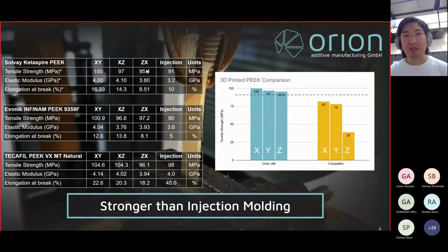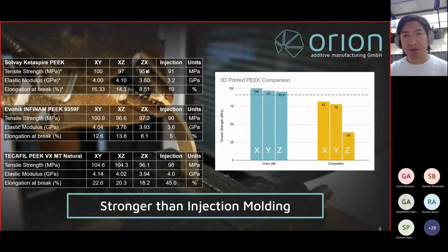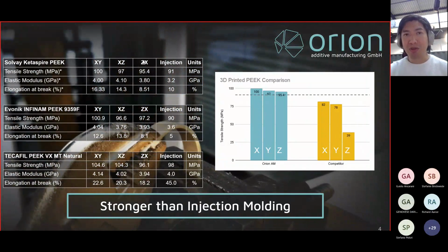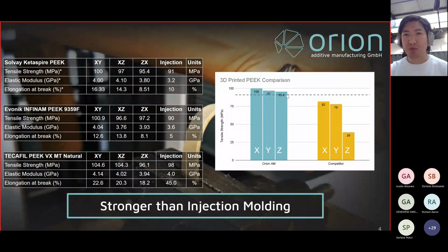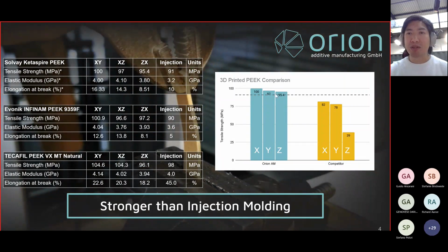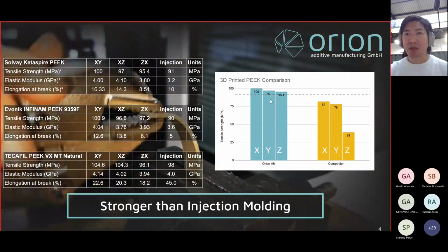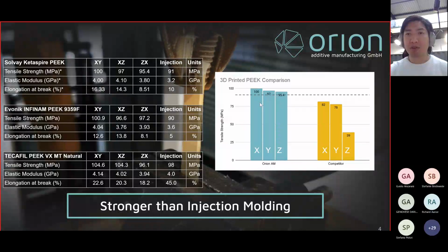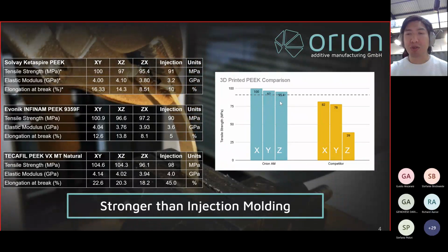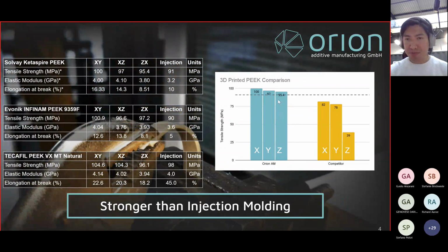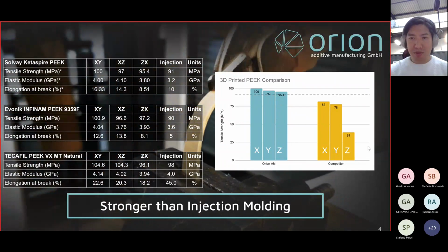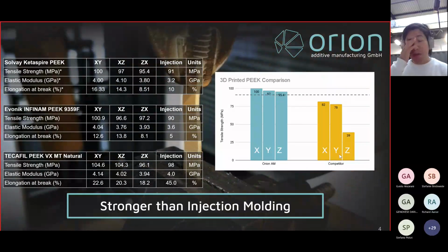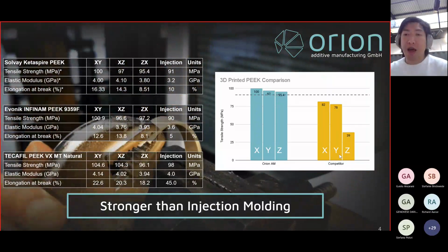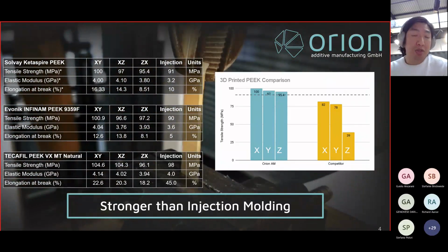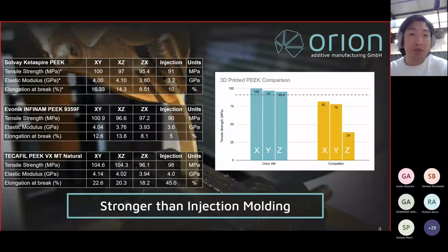It's still higher. And then on the vertical direction, this is basically pulling all the layers apart. It's the worst, weakest orientation. And even in that orientation, we're higher than injection molding. So you can see this line here represents the injection molded strength. And these 3 bars represent the different orientations, including Z, which is the weakest direction. On the right here, you see a benchmark with our competitors and how the strength differentiates using the Orion Additive Manufacturing process.